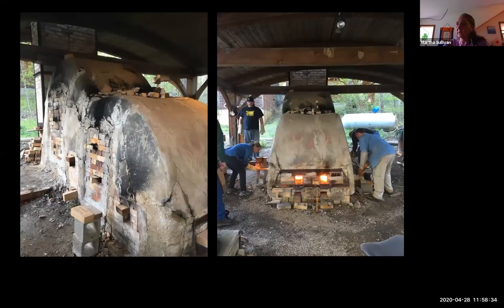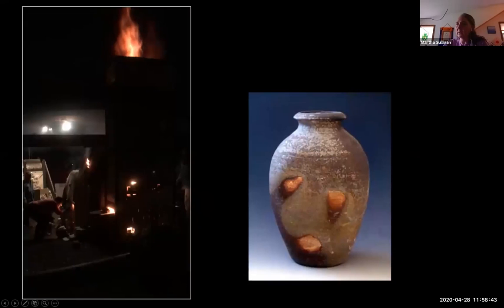And here on the right, you can see us working as a team to load this kiln up. And I don't know if I can get that little video to play for you, but on the left, it's awfully dark, but that is that 2-chamber kiln, and everywhere where you see light is flames shooting out of that kiln. So this is an experience where there are 4 different ports, and we're adding wood every 2 or 3 minutes for about 10 hours straight. Before that, it's probably every 10 to 15 minutes that we're adding wood. And by the time that the whole kiln is at temperature, the flame is so long and so hot that it's shooting up the top and out of the kiln.